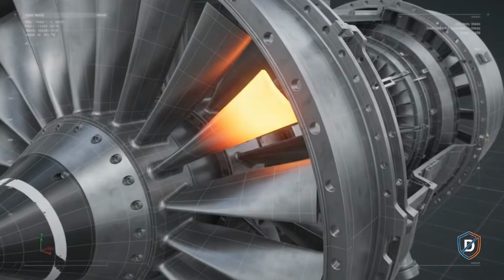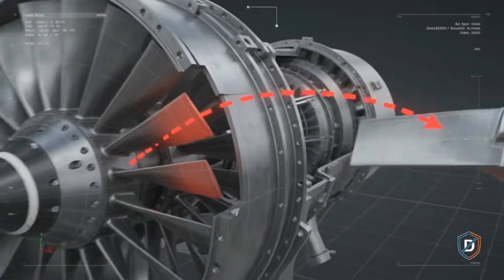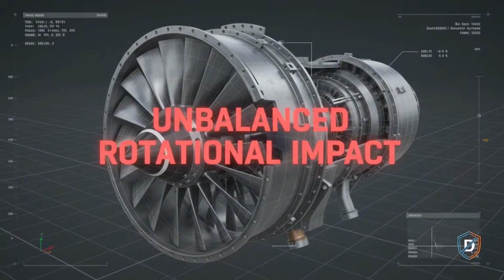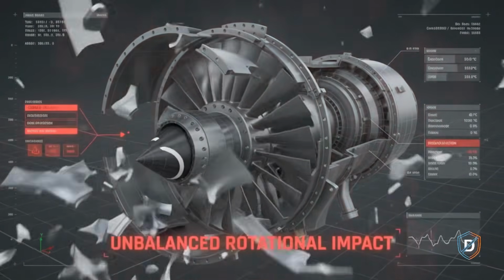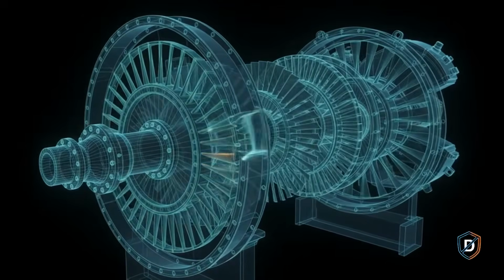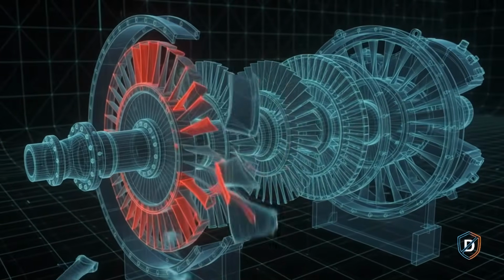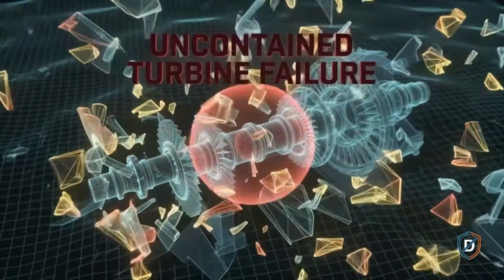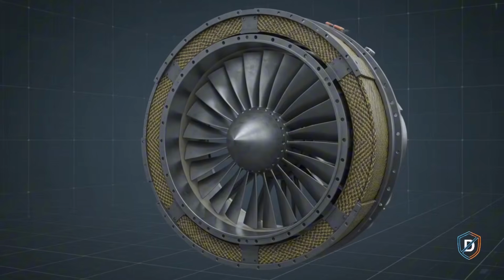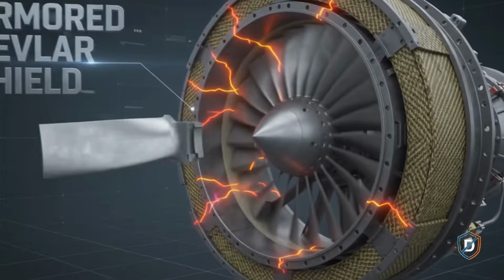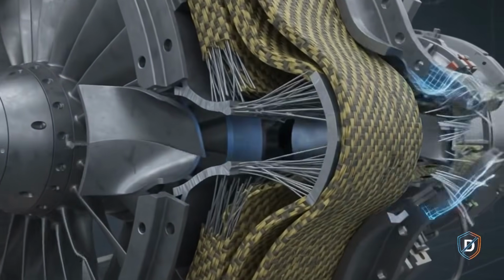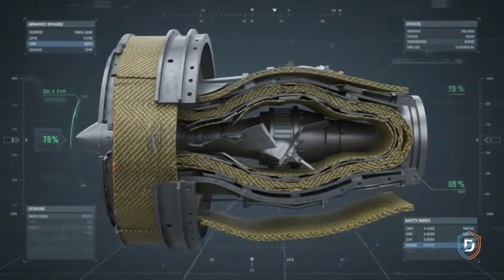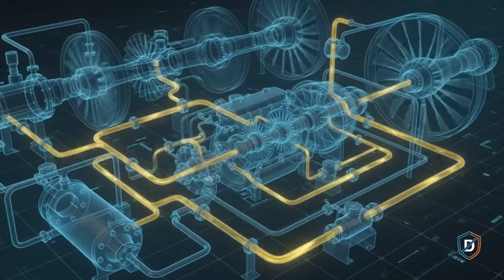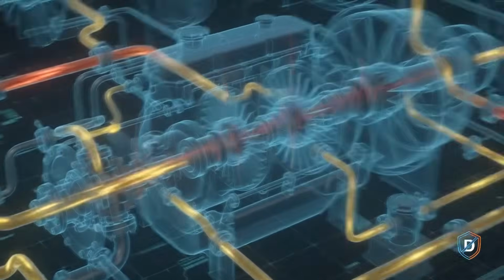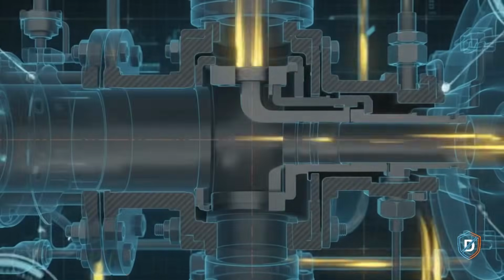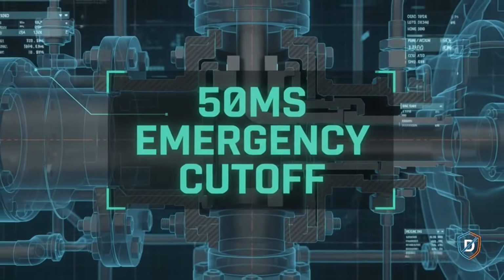As the tip melts, rotational balance vanishes. 40,000 Gs of force snaps the weakened blade, launching a metal missile into the spinning assembly. At 12,000 RPM, one broken blade triggers a domino collapse, destroying every turbine disc in 1/100th of a second. To protect the cabin, engineers wrap the turbine in a bulletproof belt of woven Kevlar and high-strength steel designed to catch supersonic shrapnel. At the same time, piezoelectric sensors detect the vibration shift, slamming fuel valves shut in 50 milliseconds, faster than a human blink.